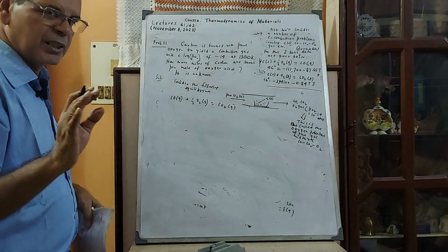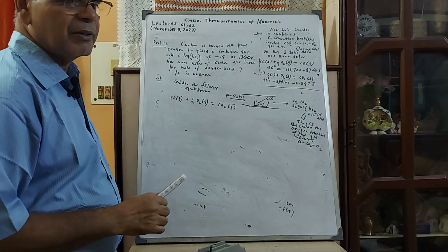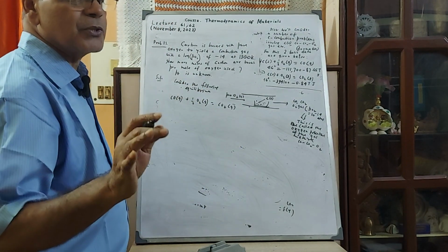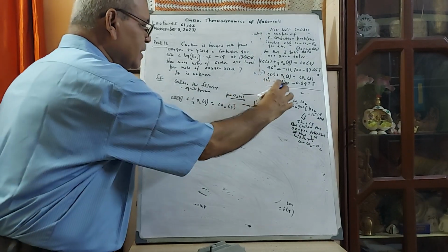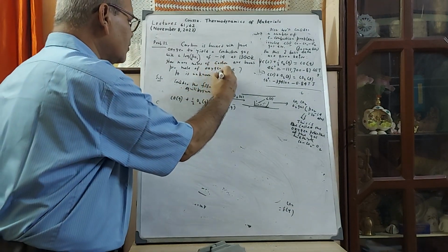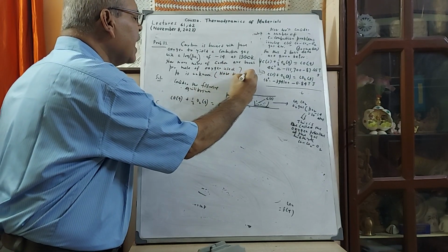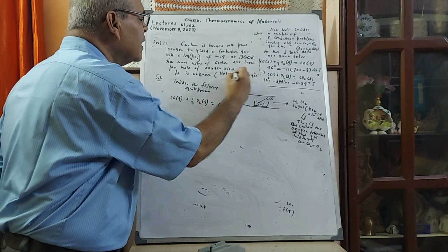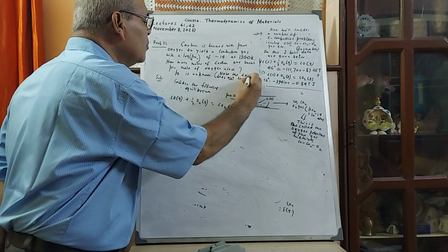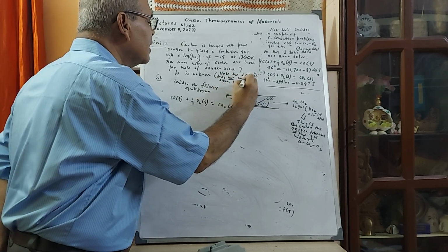You have to follow one interesting thing: this time, don't consider CO2 plus C is 2CO. This gas mixture has not attained equilibrium with carbon. It should be written. Note, this is not given in the problem, but I am helping you. Note, the exit gas does not, underline not, come to equilibrium with carbon.